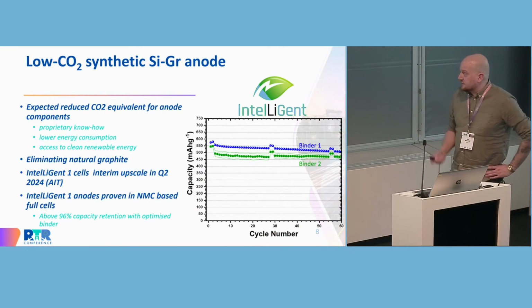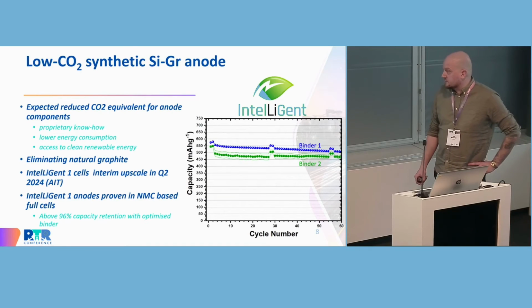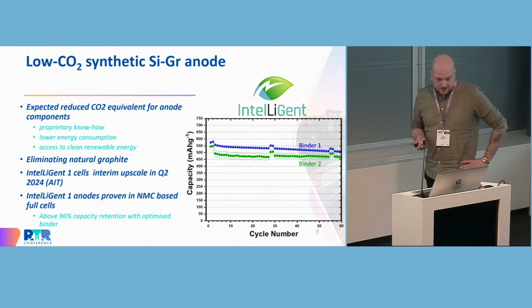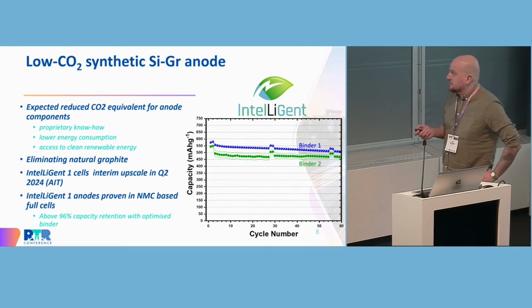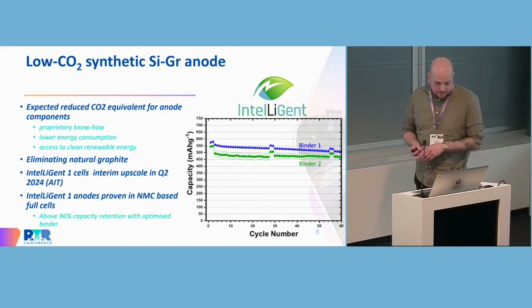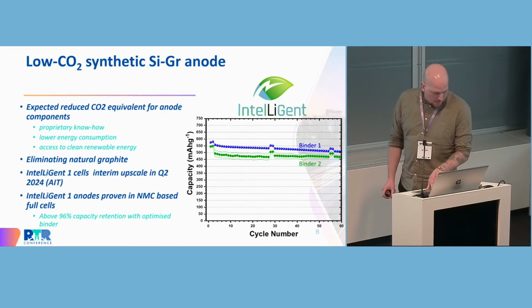And we've proven this first generation silicon graphite anode to be quite stable. So this is just the NMC based full cell versus the silicon graphite, and we have about 96% capacity retention. And the capacity is actually beyond spec. So we said we would have 450 in the first generation. We're here already at 550, and it works quite nice.